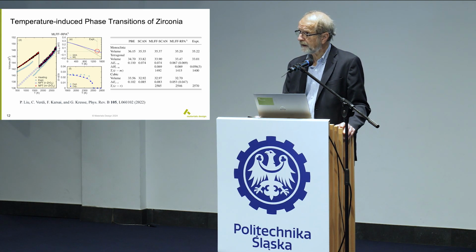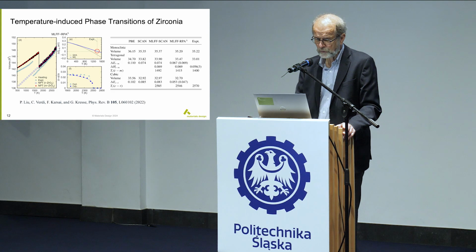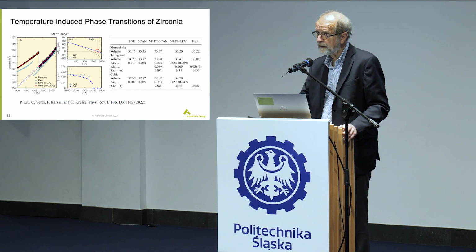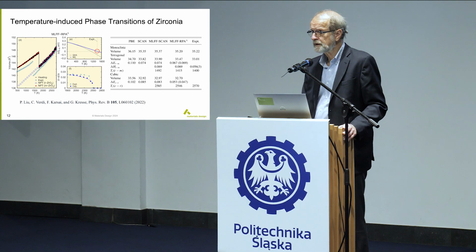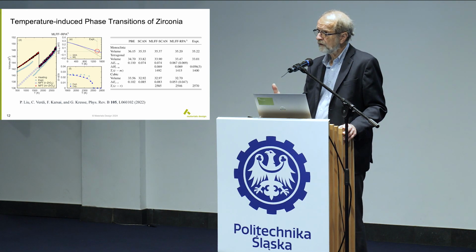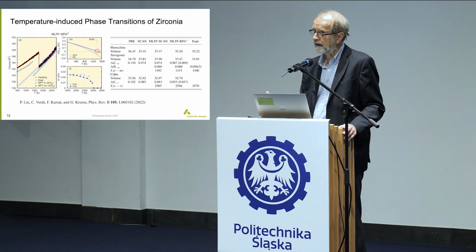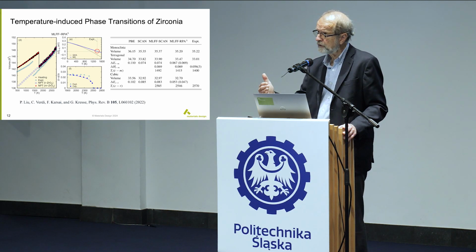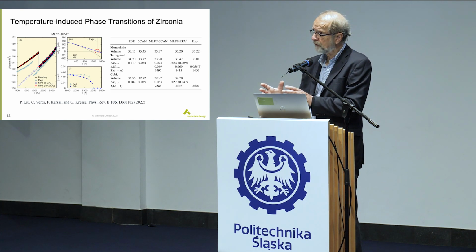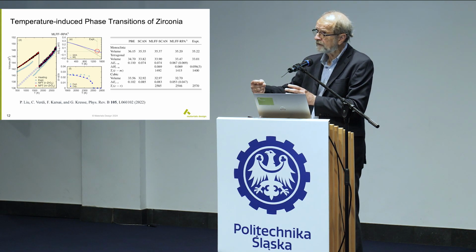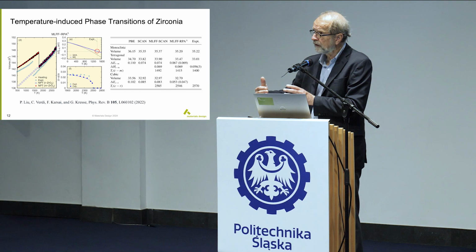And not only qualitatively, but quantitatively. That's a beautiful work done in the group of Professor Georg Kresse at the University of Vienna, using a very elegant technology called machine learning on the fly, force fields on the fly, or MLFF. In other words, he's developed in VASP the capability: you start out with a molecular dynamics calculation on the ab initio level, and at the same time you're training an interatomic potential. And as you go along, you use this potential more and more.